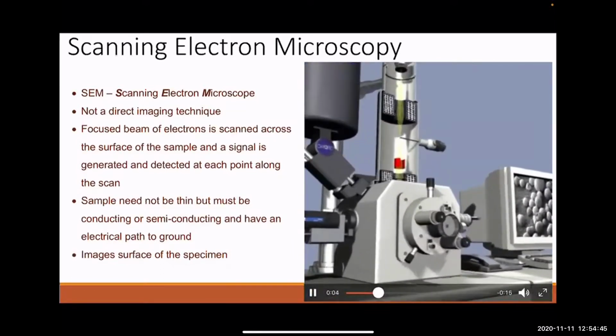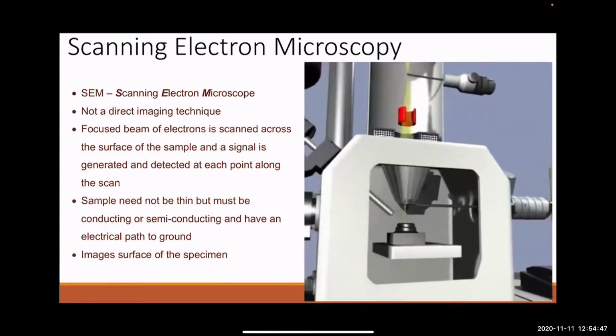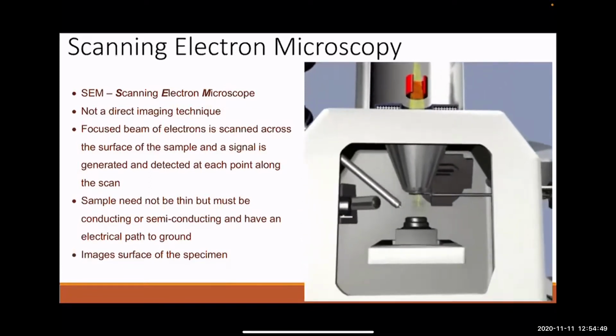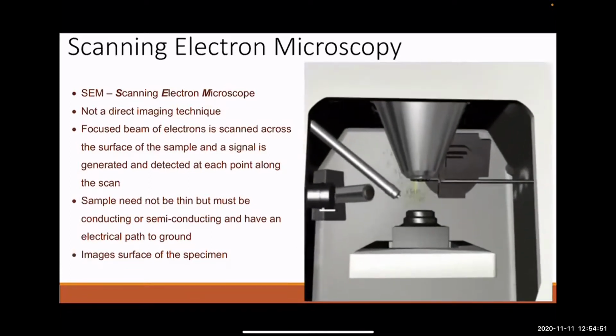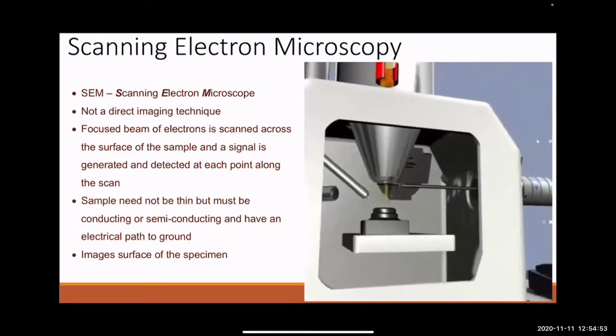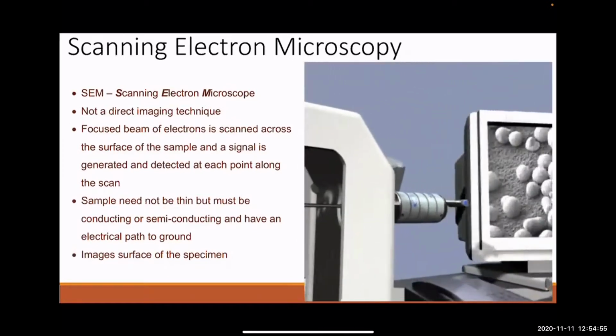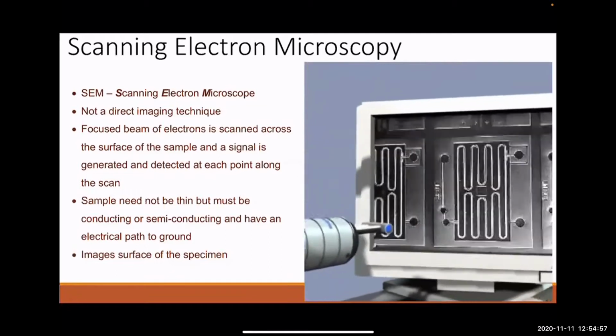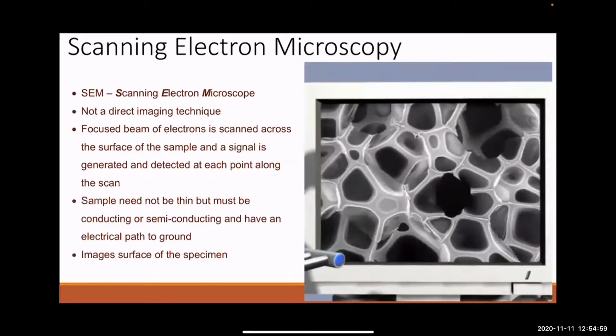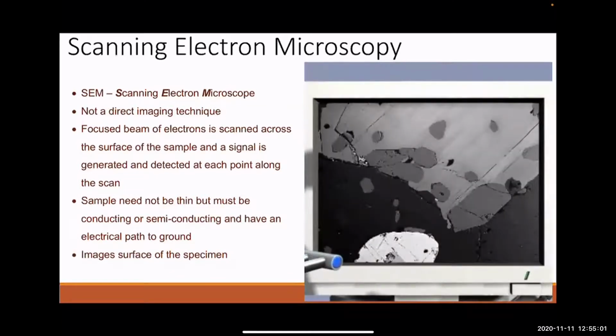In addition, your sample has to be conductive because you're radiating it with these electrons, which are negatively charged particles. And if your sample is insulating, then you're going to build up a negative charge on your sample, and you'll actually reach a point where you've got a negatively charged sample and a negatively charged beam coming in, so you'll actually repel the electrons.